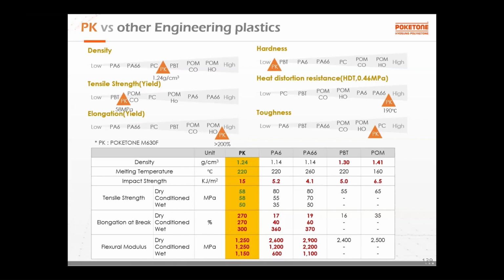And flexural modulus, unfilled base resin is around 1250 megapascal. Nylon starts at 2600 in dry, but goes down to 600 in wet. Very big change. That's why we are telling you polyketone is here, and if you have a problem, then we can give you the solution.